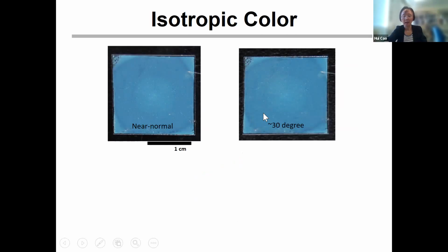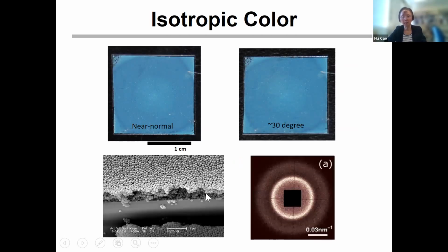And to confirm this, we actually did X-ray scattering experiments, and clearly we can see there's an isotropic ring. That means there's a dominant spatial frequency or period in this kind of structure, in these thin films, and they actually pick up this blue color to reflect in all angles.